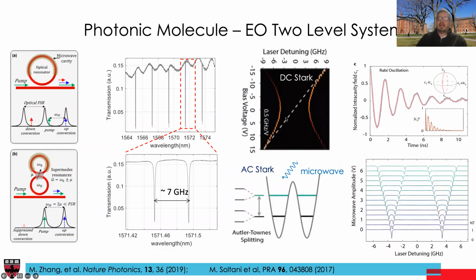Also, I can have the AC Stark effect, which is, I can apply an RF field in resonance with this splitting, either the original splitting or the splitting due to the DC Stark effect. And what that does is drive Rabi rotations in between these two optical levels. So another way to think about this is I put light in one of these resonances, apply RF field, and then light goes here, RF field is on, light goes here, here, here, and so on and so forth. And you see this shows basically transmission through this device, how light is going from one resonance to another. We put light in this resonator, turn it off, and apply RF, and you see how light is going from one resonance to another.